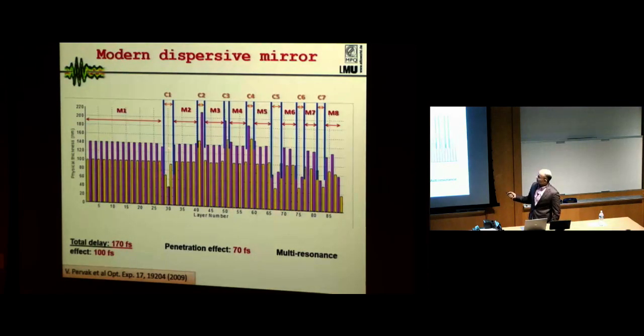And basically we have here the cavities. This cavity does not include one layer, but rather a combination of layers, because we need some certain properties for these layers, and we cannot get these properties with just one layer. We need to use a combination, but basically this combination of layers works like, you can consider three layers like one layer with a slightly different refractive index of materials and so on. It works like an effective cavity. And yes, that's basically how the structure looks.